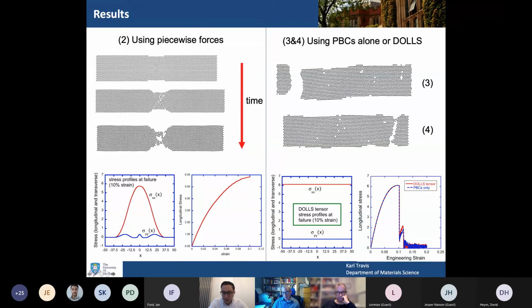So you can get the elastic modulus from the slope of the linear portion. The ultimate tensile strength is obtained from the stress at which it fails, and for the yield strength, you put a tangent to the elastic portion, move it along the axis to 0.2% engineering strain, and read off the value of the stress. So you have a convenient way of getting all the parameters you want. It's spatially homogeneous, and you don't have to do anything funny about velocities when they cross boundaries or setting them at time 0. And you've got the benefit that it's all through the equations of motion, so you can do the theory with this, and the connection with linear response theory is there.